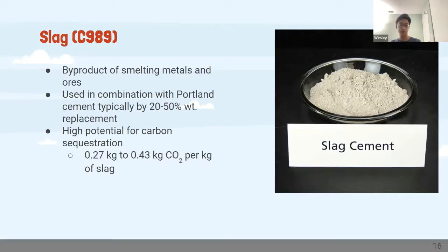And because of that, it has high potential to reduce the carbon footprint of the cement industry. So specific research has shown that using 1 kilogram of slag could reduce carbon emissions by 0.27 kilograms to 0.43 kilograms.